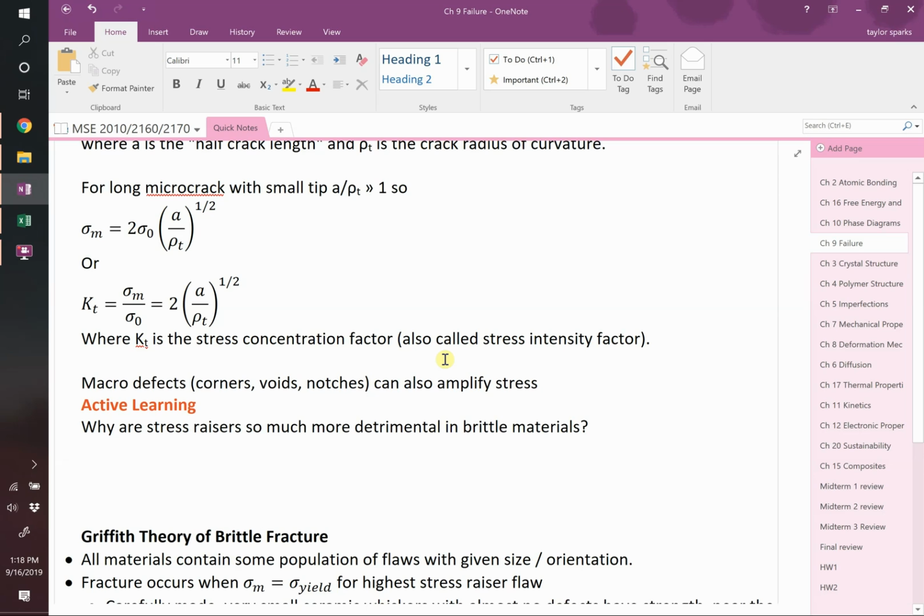So if we take this banana, right, I put a pre-crack in it, and I slowly start to bend it. Think what I'm doing is I'm bending it this way. I'm putting the top under tension, the bottom's under compression. So if I did it the opposite, I would get different deformation than if I did it this way, right? Do we agree? Because there's a flaw right here, and I'm basically prying that flaw open, versus here, where the flaw is just getting smashed together. Do you agree that if I bend it this way, it's going to look more like the Garrett banana that got all over the place? And this will look more like, well, we saw this one. It's more brittle, right?